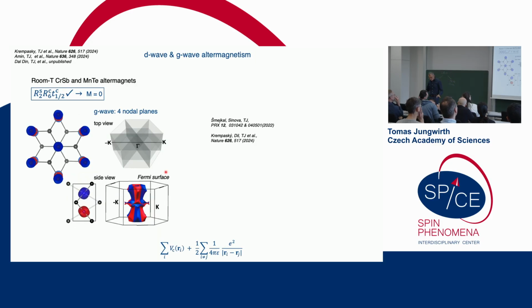So, switching gears. Now we're switching gears to manganese telluride, for which we do have convincing evidence from neutrons and from ARPES measurements that this is an altermagnet. It belongs together with the chromium antimony into this hexagonal family of systems which are not D-wave.